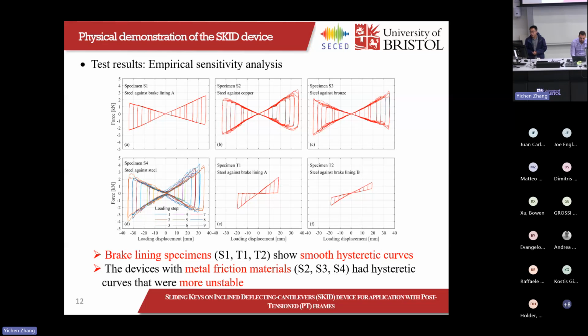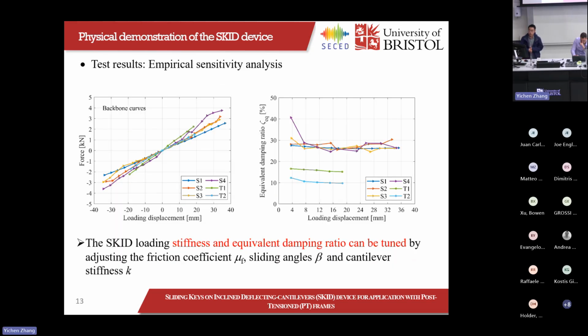Then is the empirical sensitivity analysis. I would say the most important information I would deliver from this page is that the brake lining specimens, I mean the specimens using steel against brake lining as the sliding surface, show the smoothest hysteretic curves. The specimens with brake linings are the first figure and the last two. And the red three figures are the behavior of specimens with steel against metal pads. Another piece of information from the sensitivity analysis is that the loading stiffness and equivalent damping ratio can be tuned by adjusting the parameters of the device.